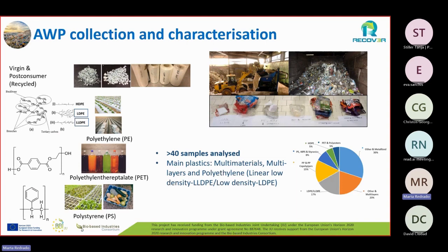And we considered not only the virgin plastic, but also the recycled one. That was the plastic that all the consortium used for the different experiments, either in film, in granules, or micronized. We also analyzed plastic in municipal solid waste and plastic coming from agriculture, more than 40 samples, and at the end we found that they were mainly composed of multi-material and multi-layer plastics, which is another block for the recycling of plastic. But they had quite a big amount of polyethylene inside.